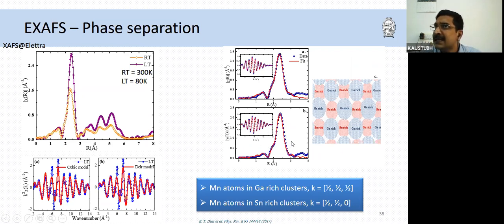So using the neutron and the EXAFS data, we could say that the ground state of this material is a cluster made of clusters. There are gallium-rich clusters and there are tin-rich clusters. And in the gallium-rich clusters, the magnetic ordering is along the half-half-half direction, whereas in the tin-rich clusters, it is along the half-half-zero direction. So the strains that the A-site atom produces actually hold on, creating this kind of local phase separation or local magnetic clusters, which could be identified from EXAFS.